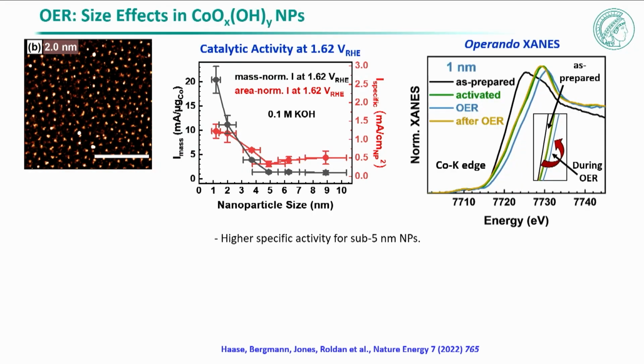And you can go to a synchrotron. This is, again, why do we need major instrumentation? You can go to a synchrotron, have high energetic X-rays, and look at this, for example, with a spectroscopy method. This is X-ray absorption spectroscopy. You have 1 nanometer particles, very small particles, and you can see from this data that the as-prepared material in black is very different from the under reaction conditions material. So this already tells you that you need these studies to understand what is happening during the reaction.